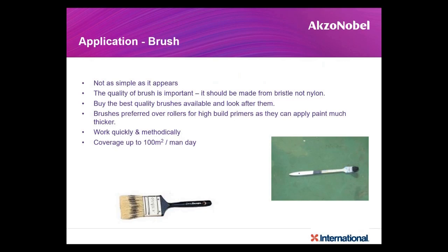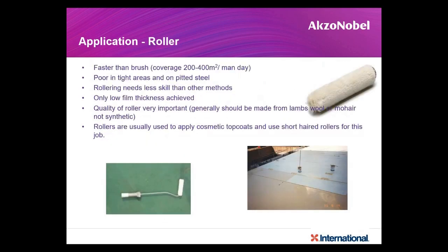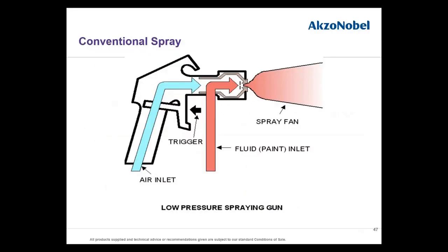So smaller jobs you can do with brush and on roller, faster. That means 200 to 400 square meters. But you cannot reach all areas. There you'll have to do a combination of brush and roller. Rollering doesn't require skill. It's a very mechanical job. Typically lower thicknesses are achieved, 40, 60, 70 microns. Quality of roller is very important. Otherwise it will leave surface finish issues. And roller is typically used once you brush apply, in order to finish, you roller it. You would have found it in your house on walls also. That's the way it is done.